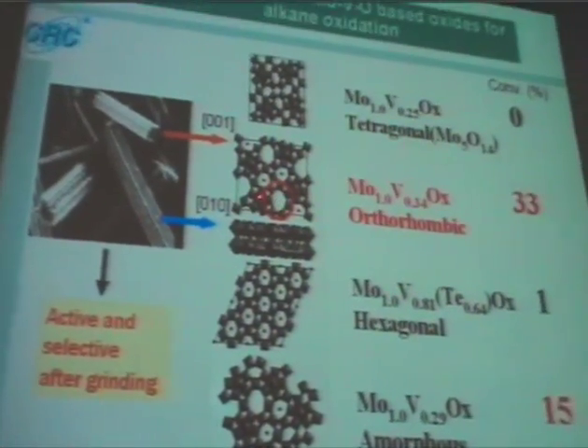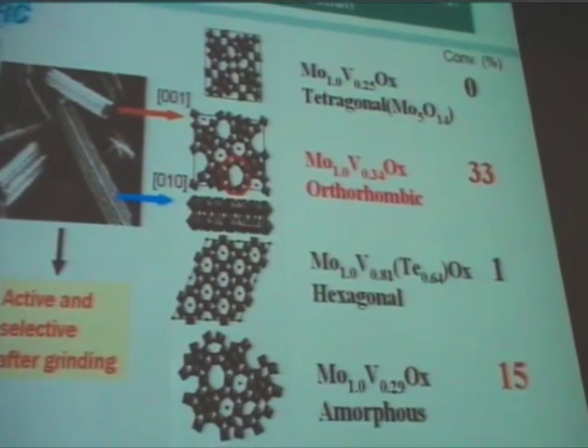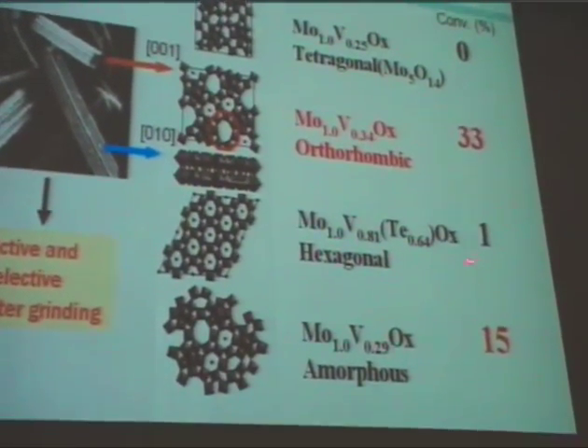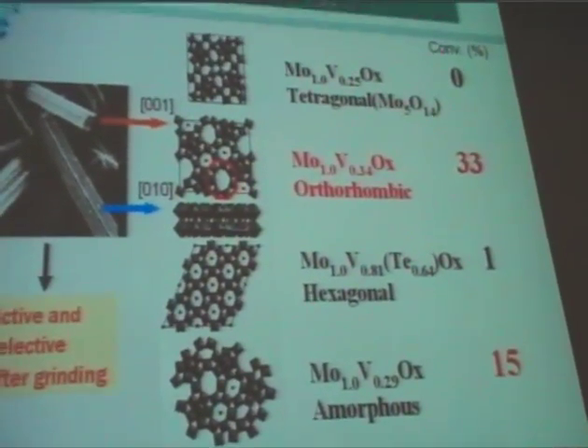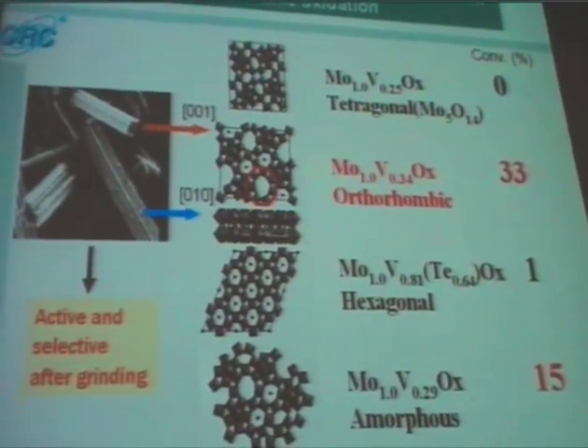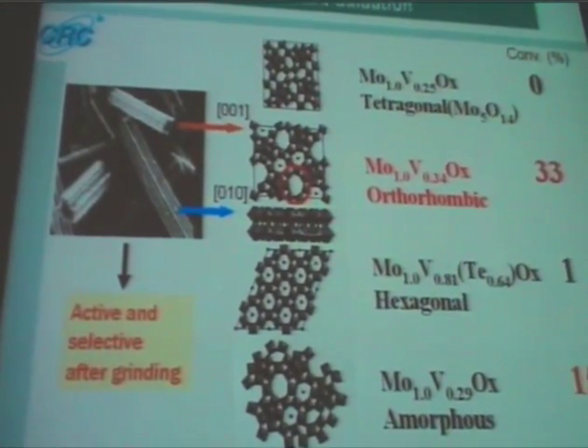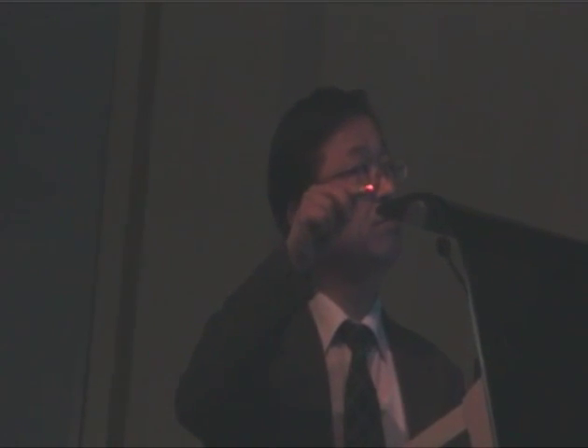For propane oxidation, this one gives nothing. This one shows very good activity for propane oxidation. This one doesn't do anything. And this will show some activity because it has an internal unit. So obviously the internal pentagonal unit is responsible for propane oxidation. This site might create some specific active oxygen species. It's not a simple mixture — it has a pentagonal unit, this is an external unit, but it has both, and additionally it also has an internal pentagonal unit as well.